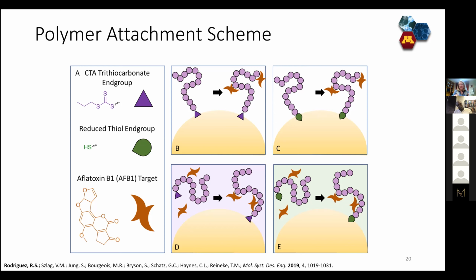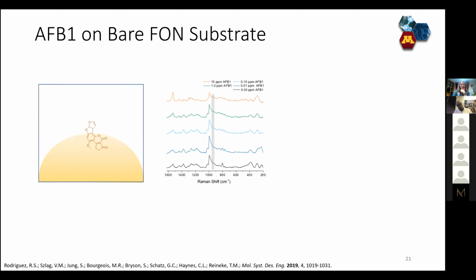And I know that sounds a little bit tedious, but when you're trying to figure out how to get the best limit of detection, you have to kind of try out all these different angles on the sensor. So let me show you some actual data now. Before we put any polymers on the surface, we of course wanted to check and make sure we even needed a polymer. So we did the control experiment first, where we just had the gold film over nanosphere, or FON, didn't add any polymer at all, introduced aflatoxin, and looked to see if we could see a SERS signal.